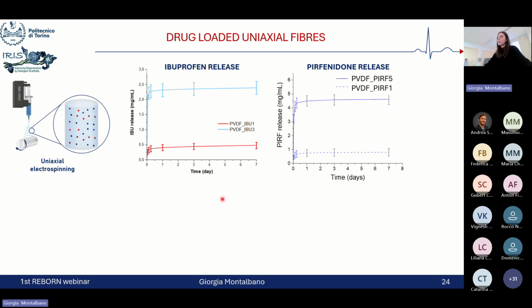So starting from the uniaxial system, we basically introduced both the drugs into the polymeric formulation by an adaptation of the initially optimized protocol in order to promote the proper solubilization of both drugs and polymer. And then the mixed formulation was processed by uniaxial setup, again adjusting the process parameters in order to obtain a stable deposition of the nanofibers.